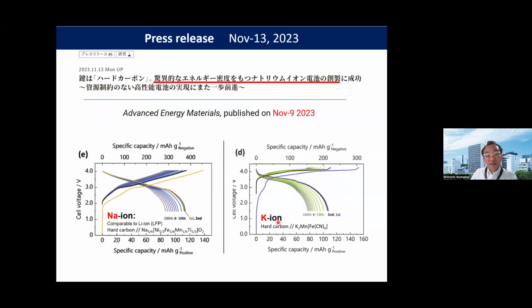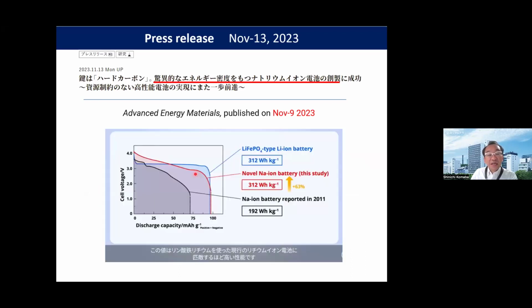This hard carbon has very, very high activity, not only for sodium insertion, but also potassium insertion. But by using hard carbon and the nickel manganese iron titanium system, you can see here 3 volt charge-discharge operation can be achieved. And this sodium-ion cell, an energy density of 312 watt-hours per kilogram can be achieved, which is comparable to the energy density of lithium iron phosphate type lithium-ion batteries. So I believe that the sodium-ion battery should be attractive as a post, low cost, secondary alternative battery to the lithium-ion battery.